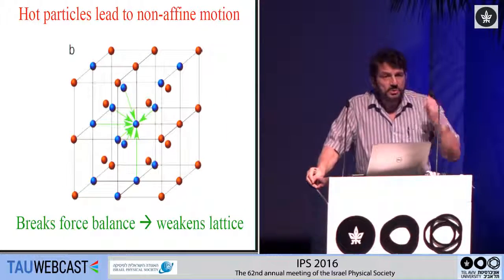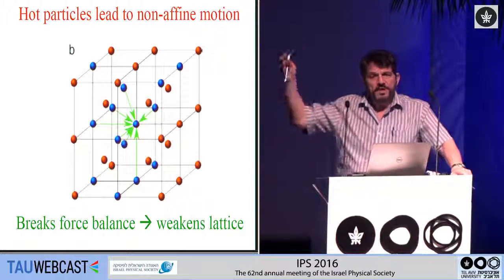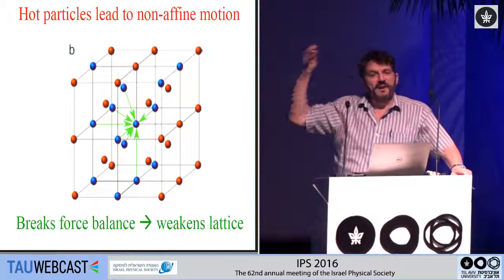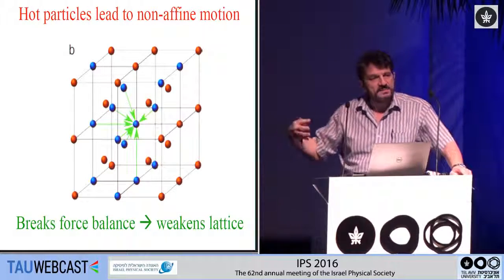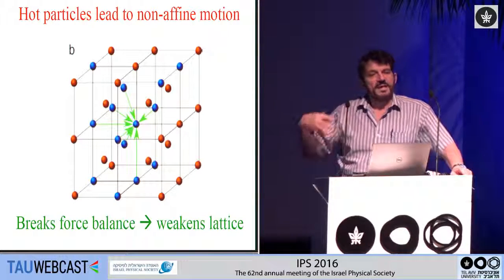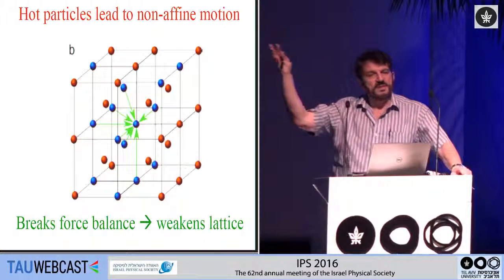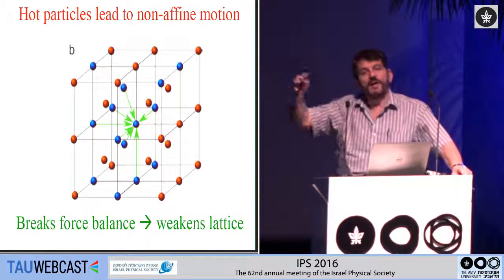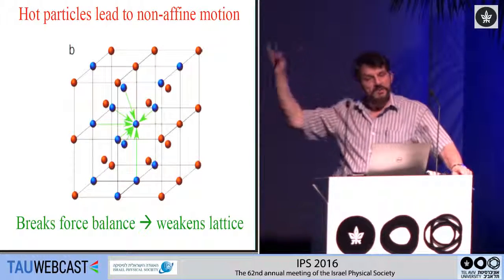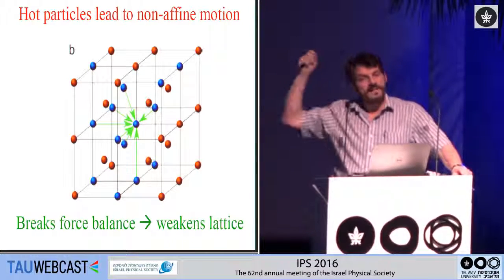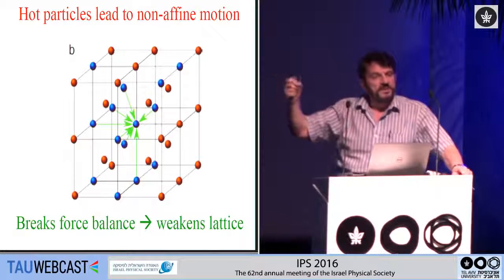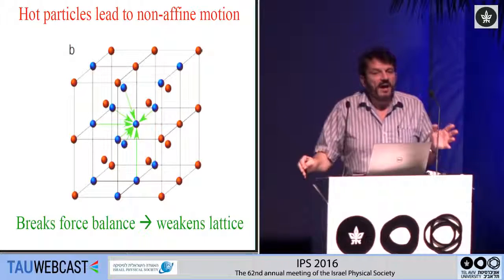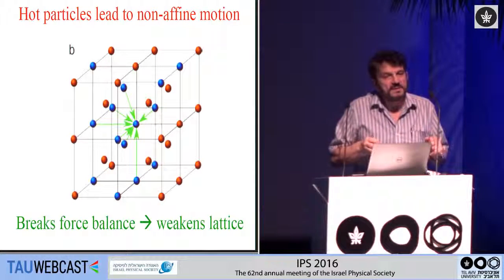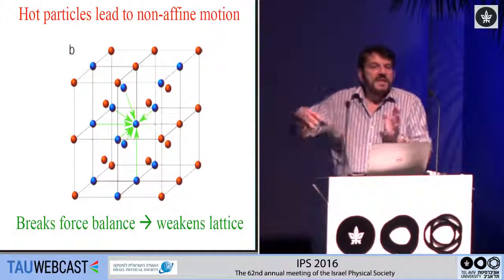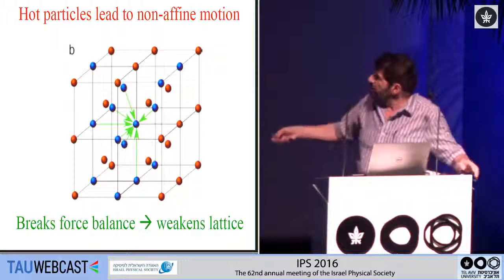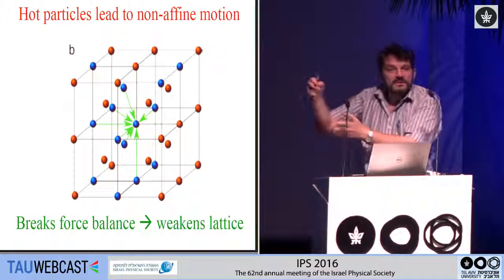So instead what we had to do was actually look at the nature of the fluctuations. And remember I showed you that the fluctuations can be enormous. They can be very, very large. And so normally when you treat systems like this, when you treat the elasticity, you treat things only in a linear approximation. The linear approximation assumes that the fluctuations, the motion of the particles, are relatively small or that they're affine. But it turns out that because the motion of the particles is so large, they're displaced from their equilibrium positions by such a large amount that any kind of affine approximation, any kind of linear approximation is no longer sufficient. And you have to extend the theory of elasticity into the non-affine, the non-linear regime. And basically what you have to do is you displace one of the particles and you have to do a force balance.